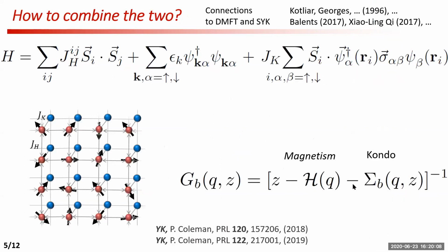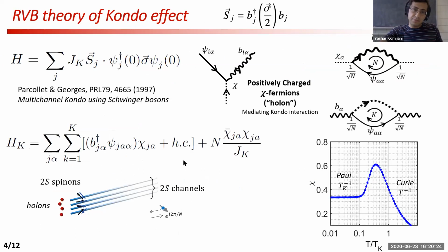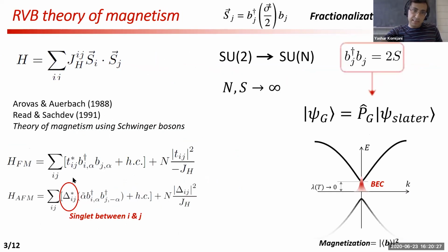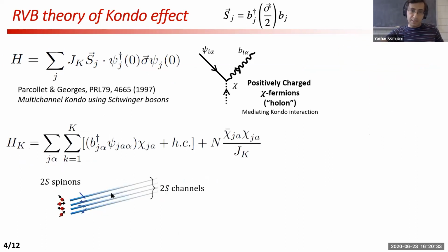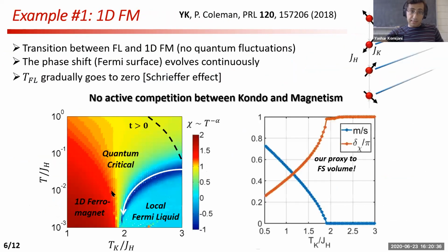However, I have to solve everything self-consistently. I also have a Lagrange multiplier that imposes the constraint softly. So I have to adjust that Lagrange multiplier to satisfy the constraint, and also update the mean field variables t and delta based on the phase diagram. So, for example, you can see here that t is the hopping of the spinons, right? So this is a transition between t equal to 0 and finite t. So this mean field parameter depends on where you are in the phase diagram.